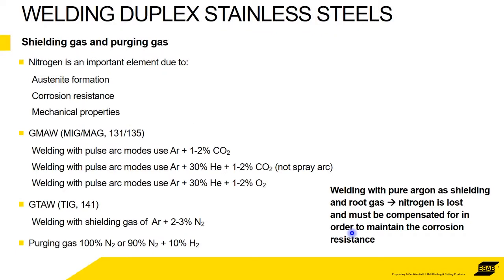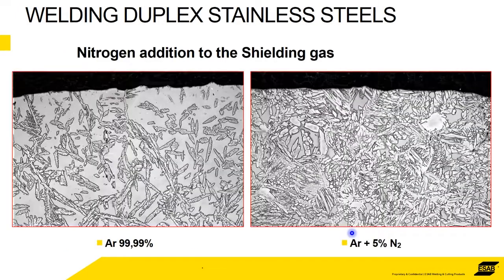In summary, shielding gas, I don't want to particularly read this out. Obviously, there were recommendations for shielding gas. One of the most important things with duplexes and TIG welding, because of the high intense heat of tungsten welding, is the addition of nitrogen. As we said, nitrogen promotes austenite. It's very fast moving, and nitrogen in the weld gives more time for the ferrite to turn to austenite. Okay, in TIG welding, nitrogen will be burnt off and needs to be compensated, and this is why.